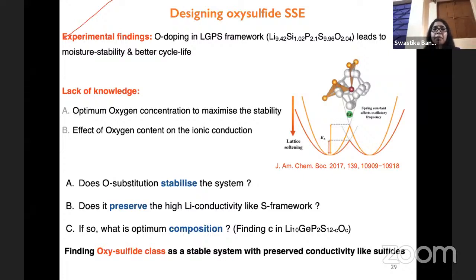That's the experimental finding from LGPS: moisture stability and better cycle life for this particular composition where you have some oxygen in the LGPS framework. However, we still do not know which is the optimum oxygen concentration to maximize the stability, and how this oxygen content affects the ionic conduction. So we wanted to ask what oxygen substitution does here, and whether it preserves the conductivity. And if it does, what should be the optimum composition? So we wanted to look for a new class of materials, the oxysulfides, with the desire for a stable framework with preserved conductivity.